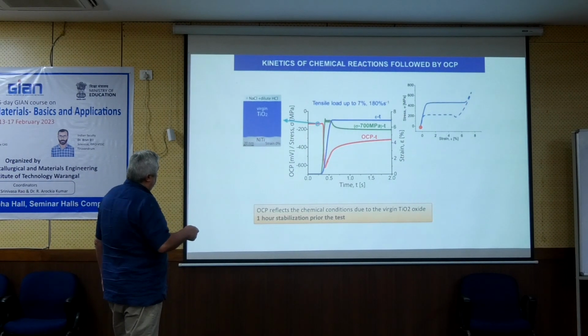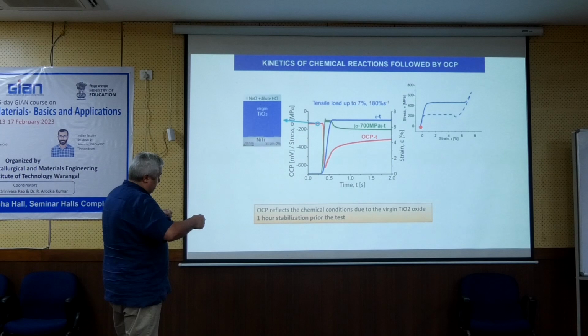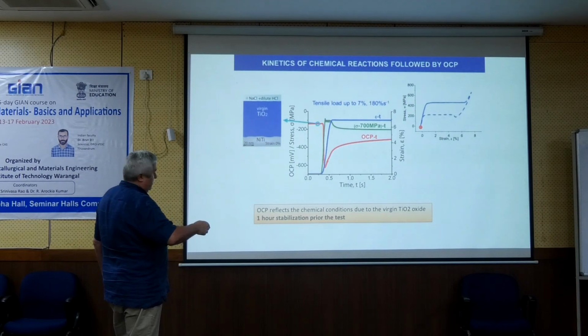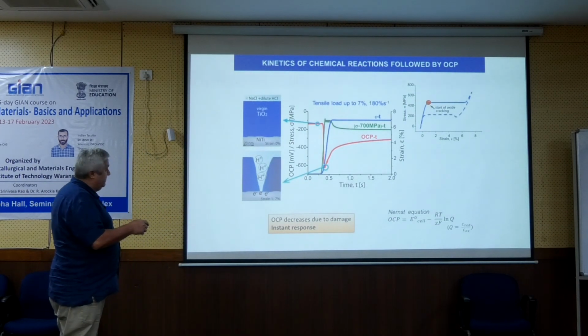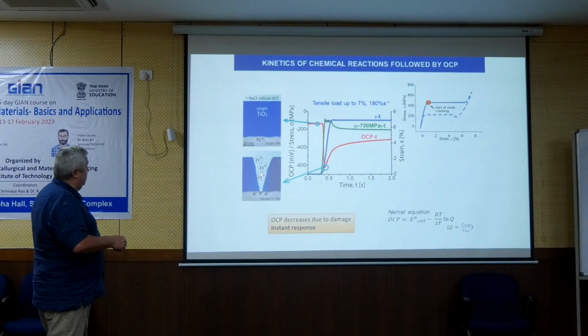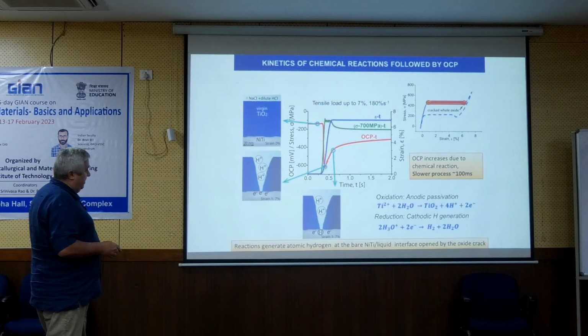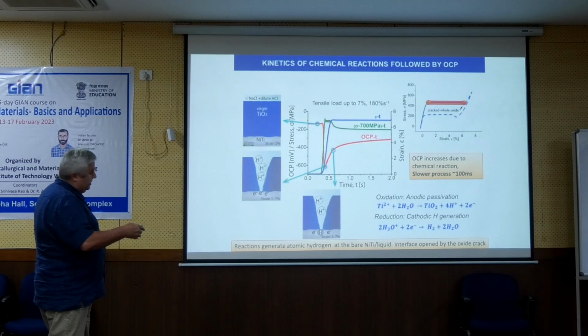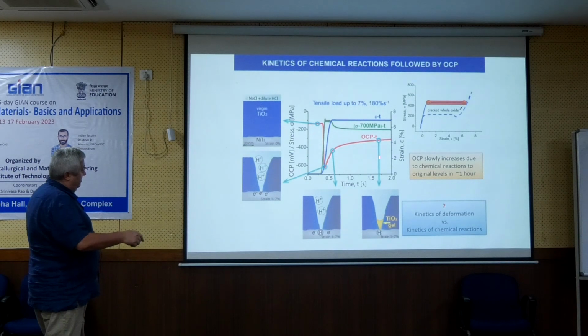So we measure the electrochemical potential, which is basically the voltage on the interface between the liquid and metal, and when we are loading, and immediately when the crack is opening, the OCP goes down, but while it is propagating, it goes up. So it can only be explained by the fact that these reactions are extremely quick, and this agrees with the literature. These reactions are really extremely quick. So after very short time, you will have such kind of healing, and after 1 second, you will have already OCP which is increasing back halfway from the value where it was before.